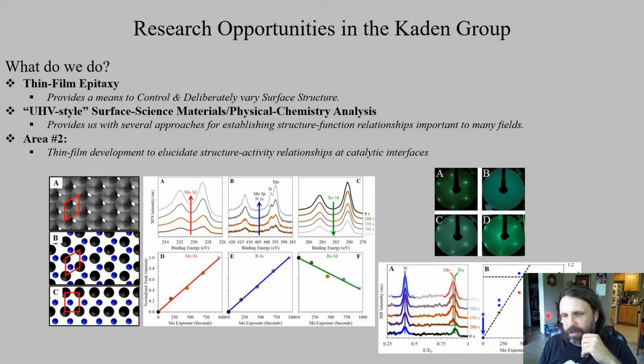So basically what we're doing is we're tracking the nitrogen and molybdenum, and we can characterize the way the intensity of those peaks grow as a function of the molybdenum exposure, and we see a clear breakpoint. This breakpoint basically is when we saturate. We saturate when the entire surface is covered with at least one of those types of things, right? And then we stop getting more. And long story short, this is basically telling us that, again, like we thought over here, we wet a layer before we grow a subsequent layer. So it gives us a good idea for how this grows.